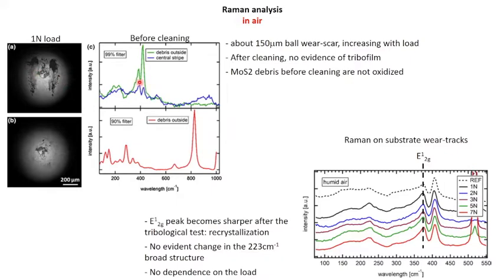And as you can see, the debris are composed of molybdenum disulfide, where there is no evidence of the oxidized layer, which has a feature around 800 cm⁻¹. It is possible to see the generation of this if we irradiate the debris with a higher power in the Raman analysis, because in this case you can see the growing of this new structure, which is related to the oxidation of the coating.